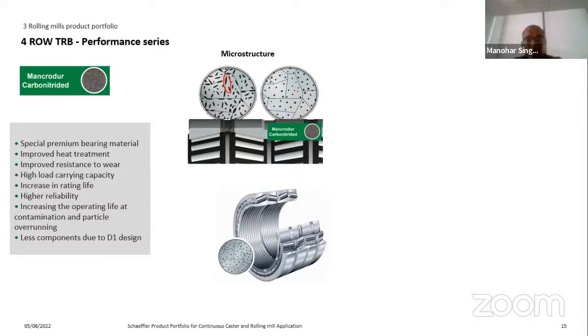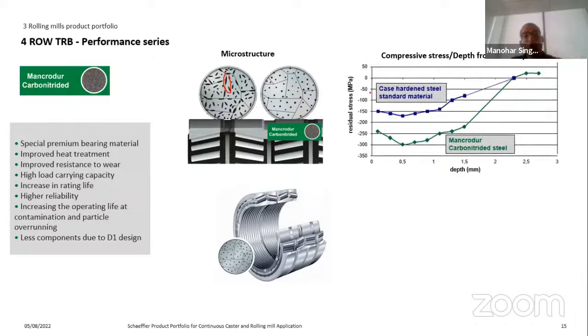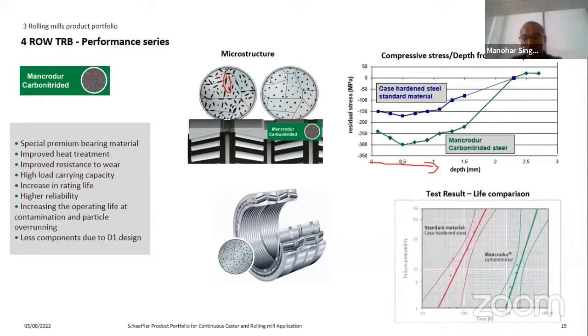So by having special material and the special heat treatment like carbon nitriding, the compressive stress is also better. This is the surface and it is the depth from the surface. So we can see that the compressive stress on the surface is also on the higher side. It means the higher will be the compressive stress, higher will be the resistance of the bearing to protect against the fatigue. So when this bearing tested and actually on the field at customer side, we have observed from the past that the life of these bearings are almost twice than the standard carburized bearing.